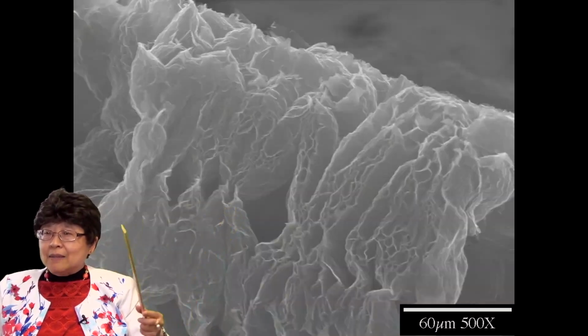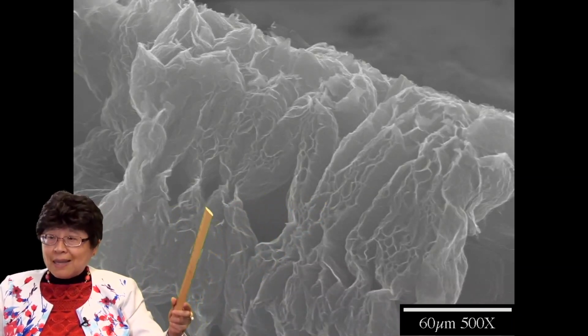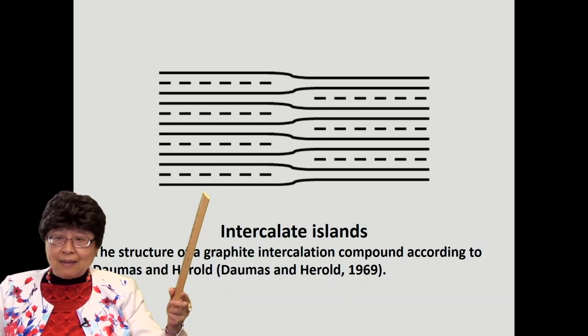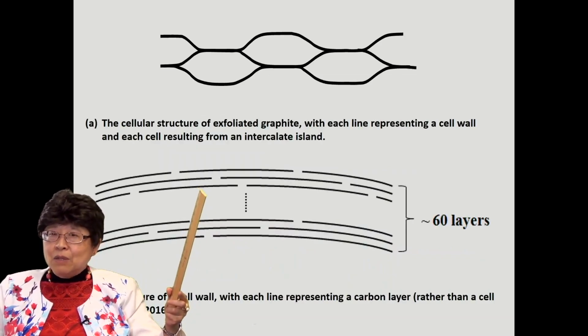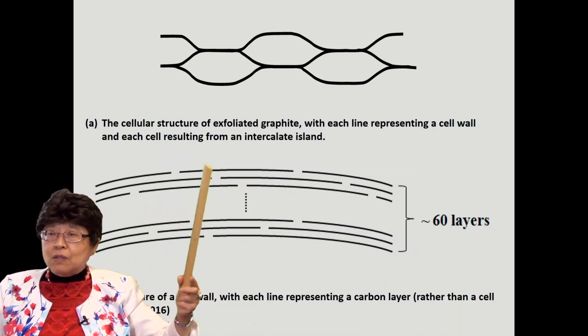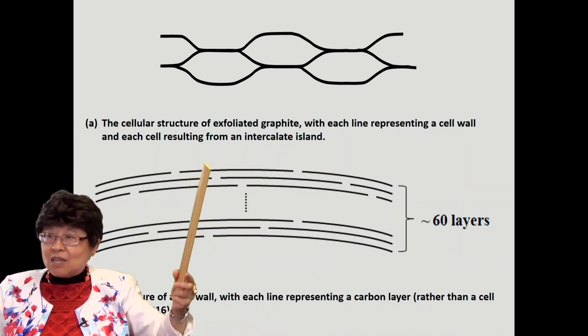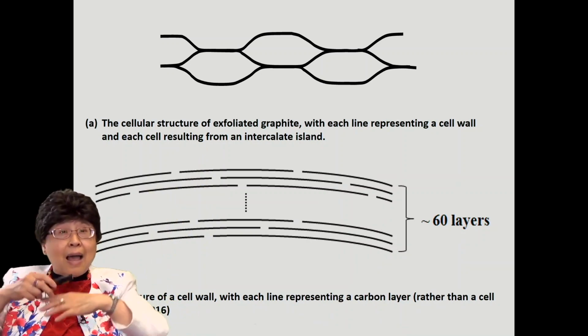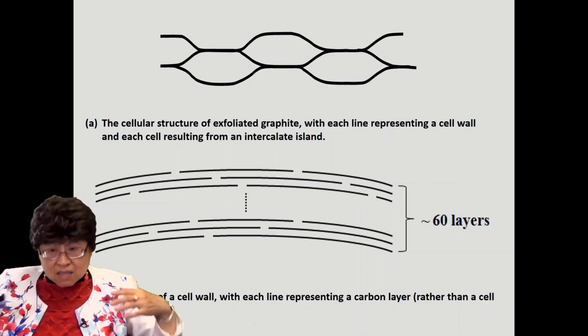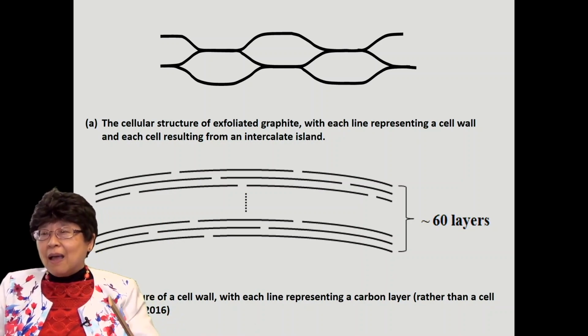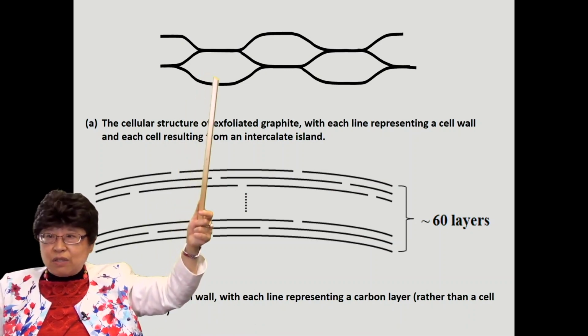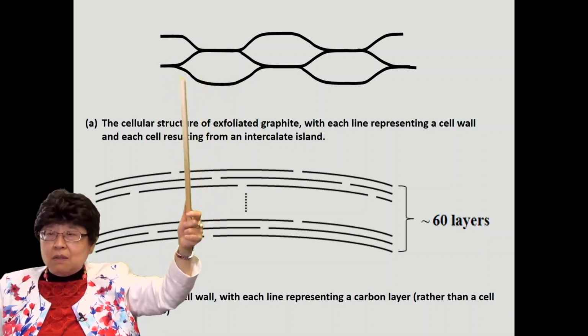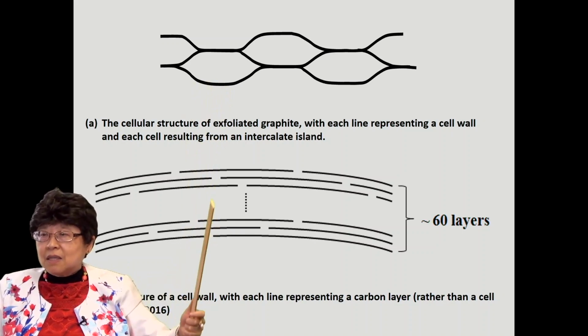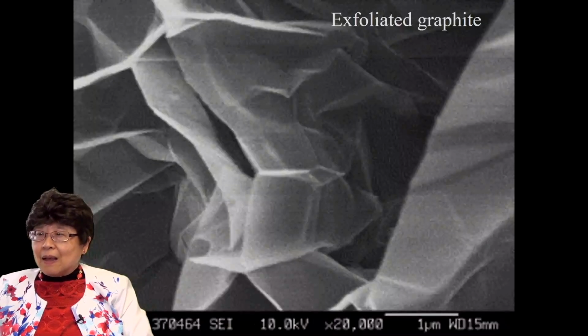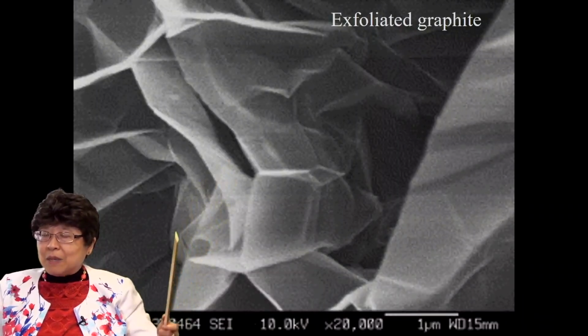And a lot of pores, a cellular structure, and this cellular structure is due to the presence of the intercalate islands. The islands just expanding because the intercalate wants to vaporize, it's just ballooning up. And the ballooning is possible because the wall of the balloon involves a number of carbon layers, say 60 carbon layers. And the carbon layers can slide relative to one another. So the balloon wall can stretch a lot due to the sliding of the carbon layers among one another. And this is the cellular structure. And the solid line is the balloon wall, the wall of the cellular structure. And this wall can consist of, say, 60 carbon layers. And this is the exfoliated graphite that has been greatly exfoliated.